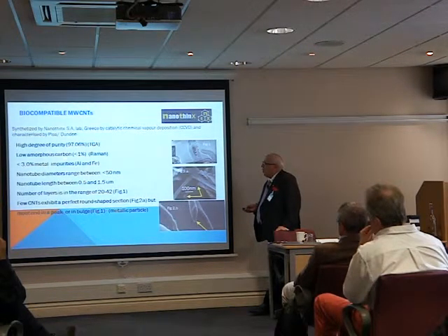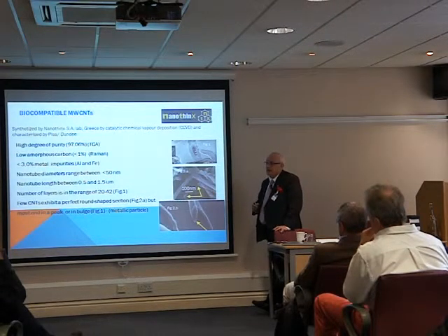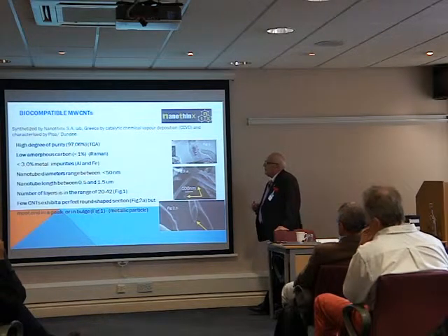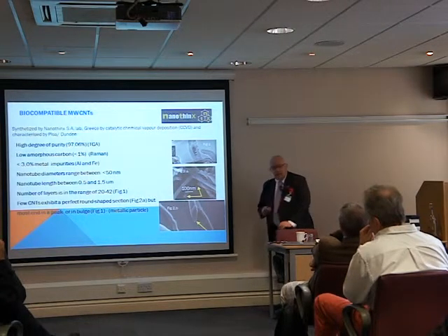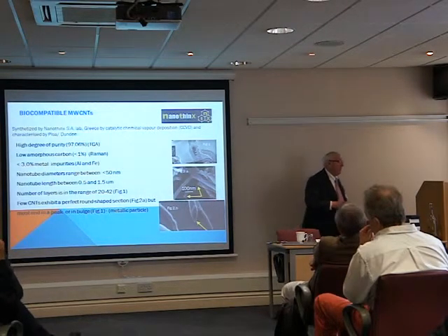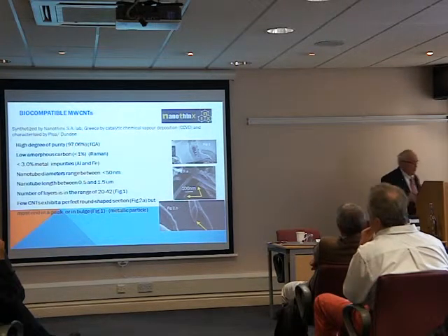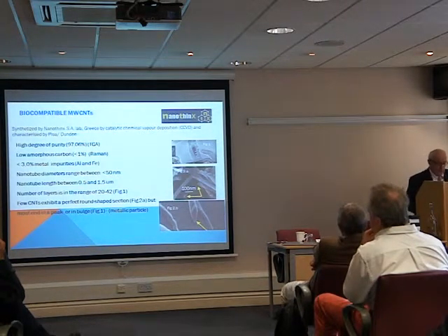Have to have low amorphous carbon content. Again, you have to quality control this to less than 1%. Preferably less than 3% metal impurities. The higher the metal impurity, the more toxic it becomes.